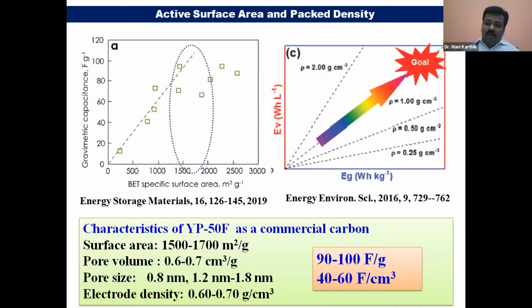If you have very little material loading, your material may give high gravimetric capacitance, but not high volumetric. If you have more material, another technological problem comes: if the material is not well adhered to the current collector, it may peel off. These are the optimization parameters we need to handle for commercial purposes to get very high performance supercapacitors. At the state-of-the-art commercial level, it is 90 to 100 farads per gram. With an electrode density of 0.6 to 0.7, you get around 40 to 60 or 70 farads per cubic centimeter.